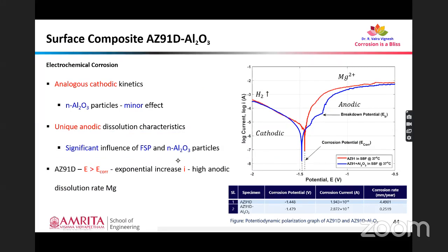In this we have done the potentiodynamic polarization method only. The electrolyte used was synthetic body fluid based on Dulbecco's phosphate buffered solution. The potentiodynamic polarization plots are shown here. The red colored line indicates the potentiodynamic polarization plot of the base material, and the blue colored line shows the potentiodynamic polarization plot of the prepared surface composite.